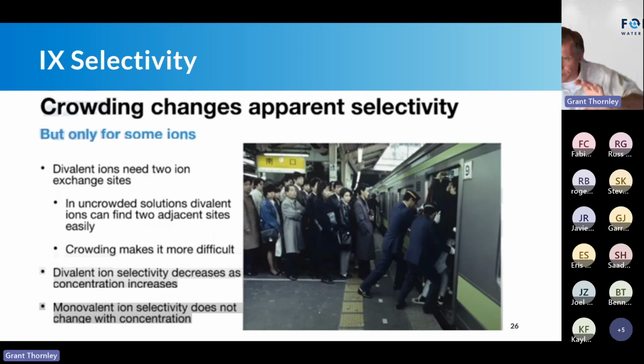So think of it as there's a lot of crowding on the ion exchange. Monovalent ions, like lithium, are different, because you have a single site, and there's lots of single sites. So no matter where, again, if I'm going into the movie and it's only me, and there's only single seats, I can sit anywhere in the single seats. So that's key. Monovalent ion selectivity does not change with concentration, but divalent selectivity does decrease with TDS.